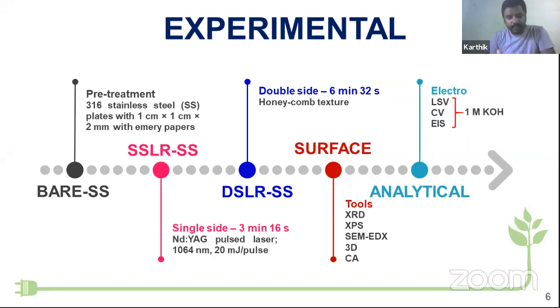Honeycomb texture has been drawn over one side of the stainless steel. Then the resulting substrate is abbreviated as SSLR. The expansion is single side laser irradiated stainless steel. When it is irradiated on both sides, that is double side, it requires 6 minutes 32 seconds, whereas for single side irradiation, you need 3 minutes 16 seconds. So the resulting substrates are termed as DSLR, that is double side laser irradiated stainless steel.